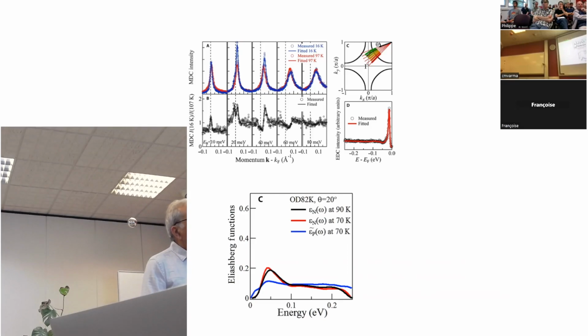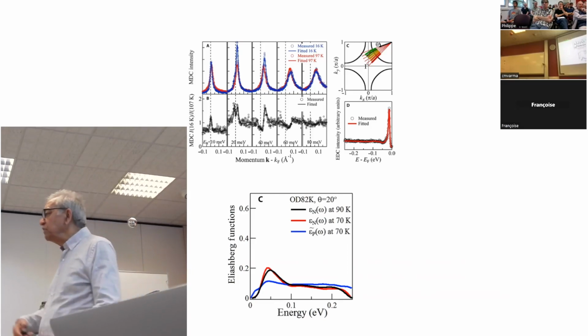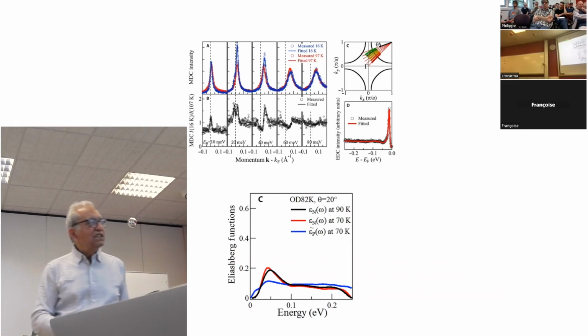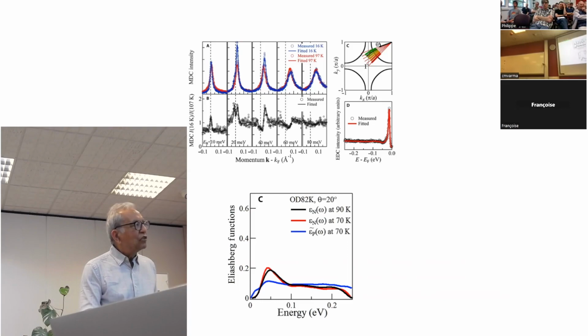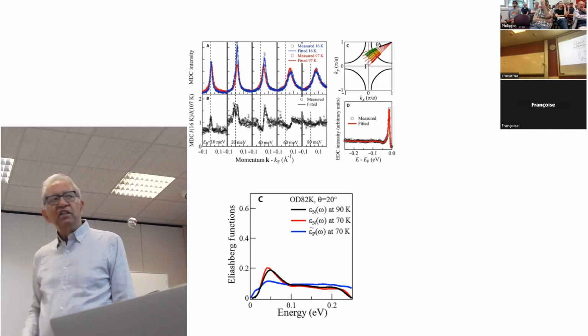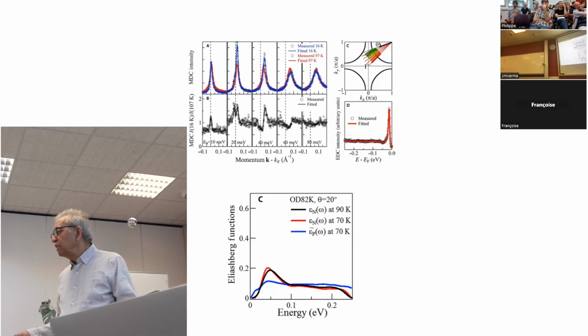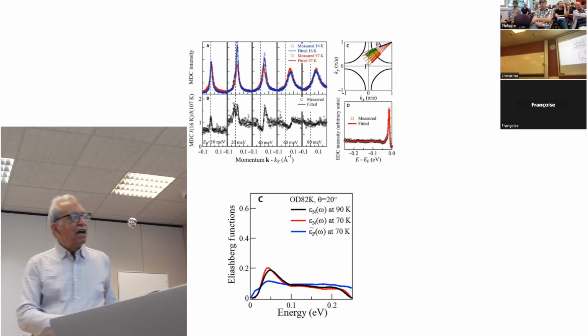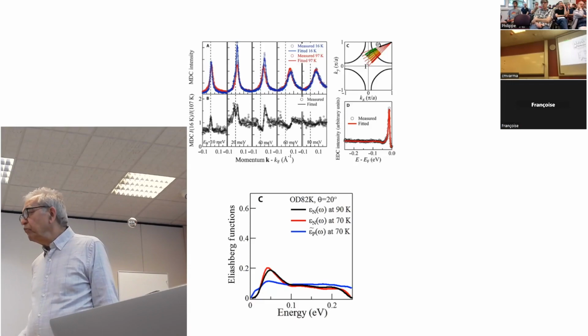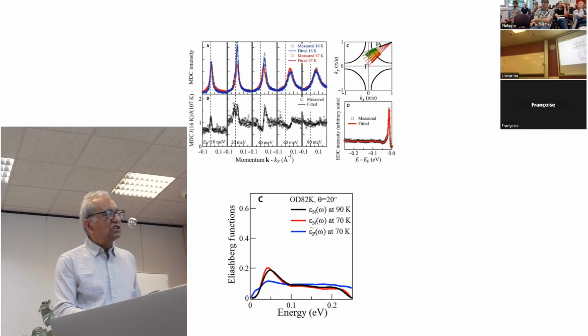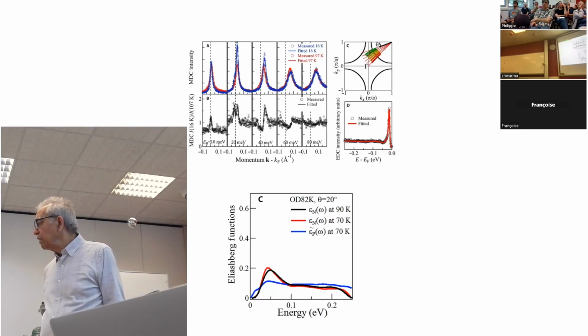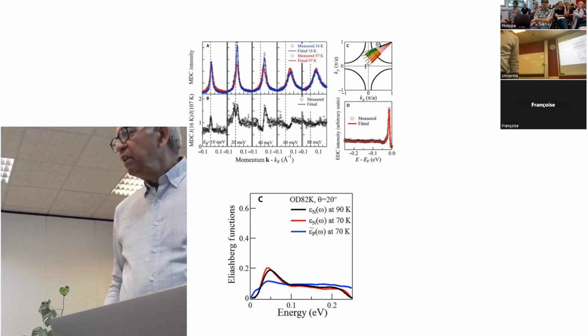So this is the normal fluctuation spectrum, which gives you this normal self-energy that looks like these two curves, 90K and Tc is 82K. And if you look at the pairing object, it looks like this. And I think there are errors of at least 20% in each of these. But you can say that apart from this bump, which is probably due to some phonon, which I do not understand, this fluctuation spectra is a bit like what we suggested causes the whole game.